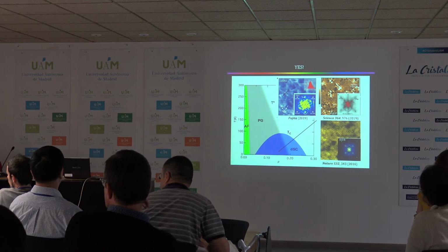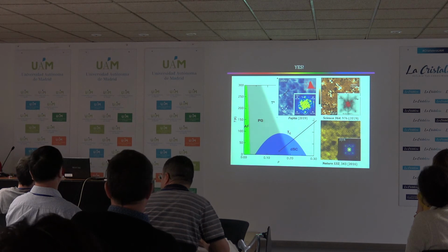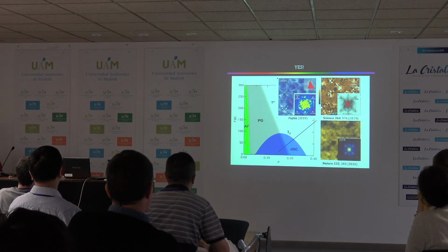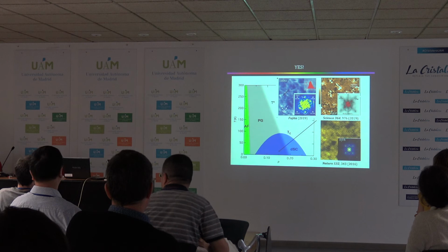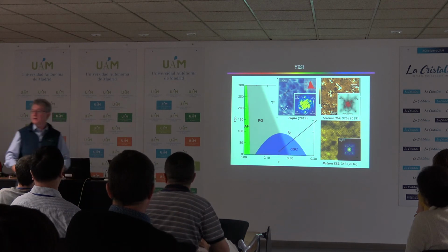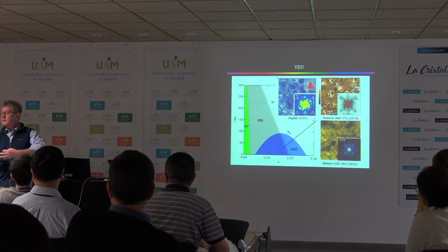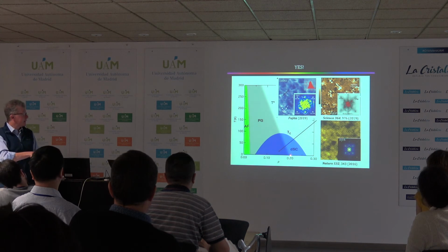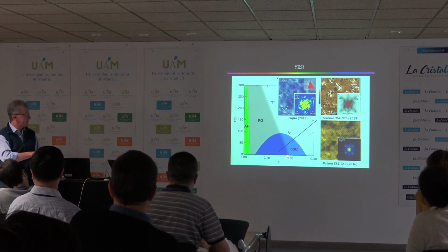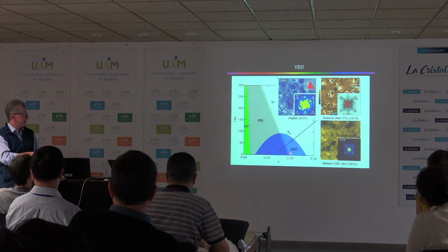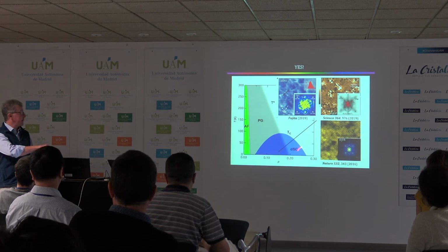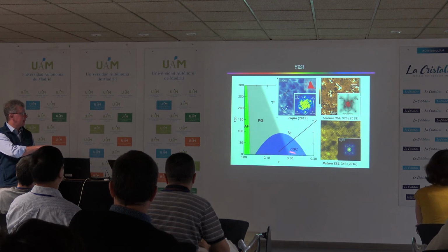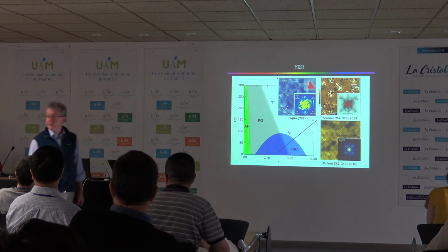Before you go to finite temperature and pseudogap, it seems from your picture that you have a dark blue region and a light blue region in the superconductor. Do you see a pair density wave only for certain dopings and not for others? Yes. There's a critical point here at 19%, where 5 years ago or more, we examined what happens to the density wave and the momentum space electronic structure. There is a sudden transition, a disappearance of all density waves here in 2212. At the same time, there's no reconstruction, no transformation to a new Fermi surface. So as far as we know, and as far as our techniques can detect, there's no pair density wave on the other side. Thank you for that excellent question.